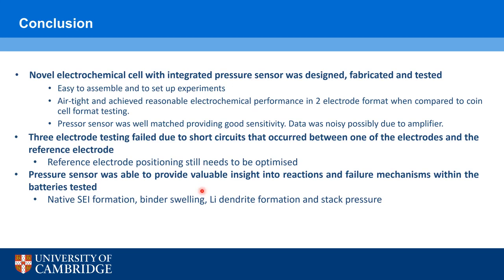And it seems that, at least in the 2 electrode format, a few tests to optimize the stack pressure could allow us to have some nice long term testing to look at the changes in pressure in a 2-electrode cell.